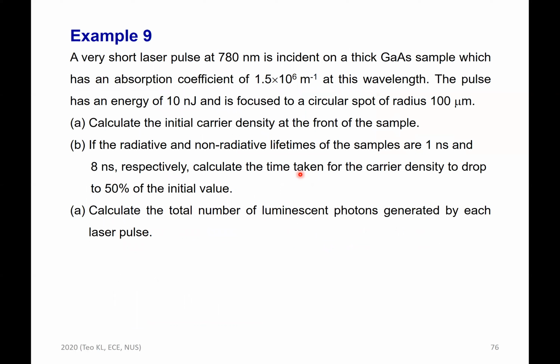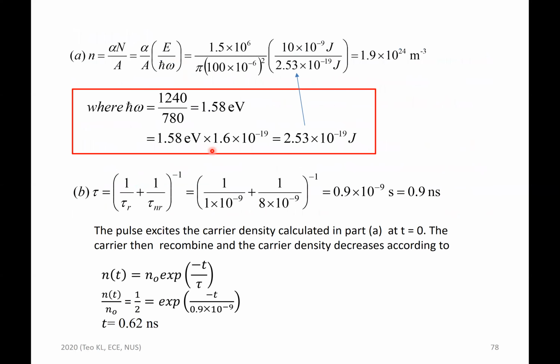Calculate the time taken for the carrier density to drop to 50% of the initial value. Now, in this sample, you also have a non-radiative lifetime, which means there are also defect states. So the effective recombination lifetime will depend on the radiative and non-radiative lifetime. You just need to plug in these two values, and you get about 0.9 nanosecond for the effective recombination lifetime. So this carrier concentration is at time equal to 0, generated at the front surface.